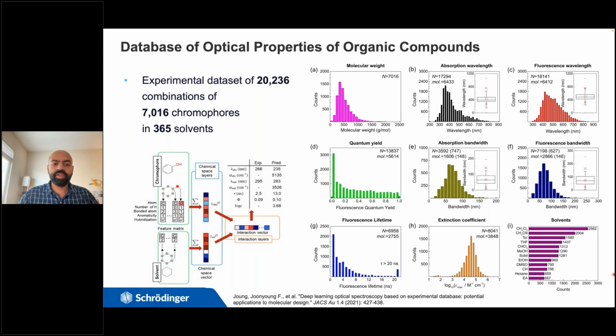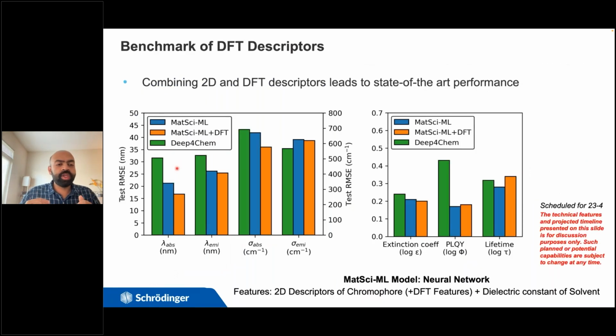So we also wanted to tackle this data set and come up with our own solutions. What we did was we calculated the 2D descriptors for the chromophore and the 2D descriptors for the solvent, and we concatenated the two. In addition to that, we also generated DFT descriptors for the different chromophores. What we noticed was that this approach of using a neural network by combining the 2D descriptors for solvent and chromophore seemed to outperform the model reported in the literature. Deep4Chem is the model performance that was reported in literature. The MatSci-ML is our internal Schrödinger model, which is based on the concatenation of the solvent and the chromophore descriptors. And the MatSci-ML DFT is our Schrödinger model, which combines DFT descriptors of those chromophores.